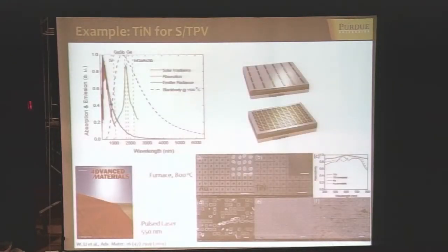So this is just to illustrate the point. It's a very simple structure which we built. It works as a perfect absorber when you use these titanium nitride rectangular rings—it could be different structures, we just used this one. You could see it absorbs the whole visible part of the spectrum coming from the sun, and the absorptivity is very close to 100% as needed.